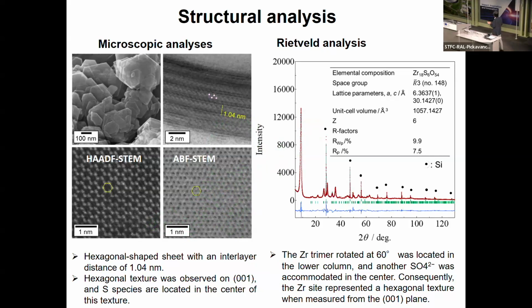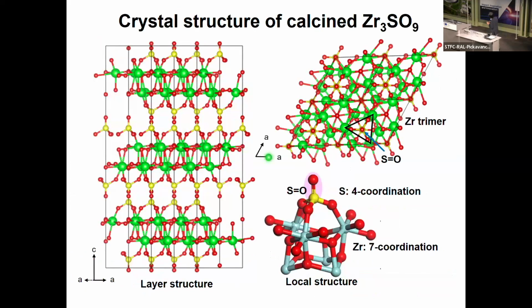Based on this kind of information, we conducted Rietveld analysis and then confirmed the structure. The structure is like this. This is the layer structure. If you look along the C direction, the 001 direction, you can see this kind of elemental distribution. You can see the triangle on this, yeah?